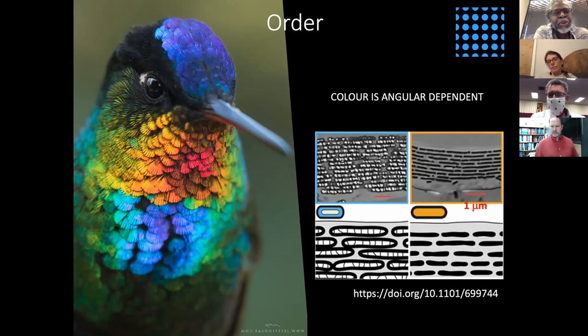So that same principle applies to butterflies, for example? Yes. But the most famous butterfly, like this morpho butterfly that is blue. In this case, you have a photonic structure that is obtained without pigment. But you have a layer underneath. So you have two scales. You have one scale on the top that has the photonic structure, and then you have a second scale underneath that is what gives you the pigment. Because you combine it to give color depth. Essentially.